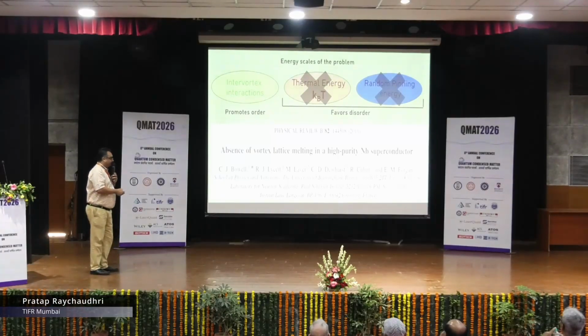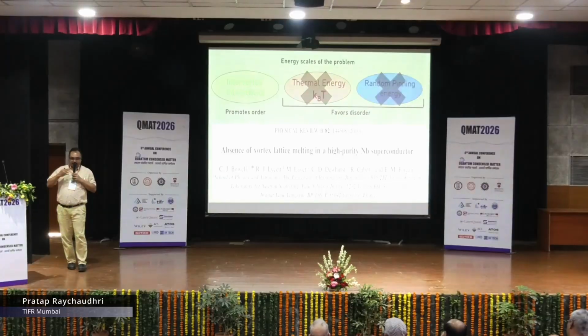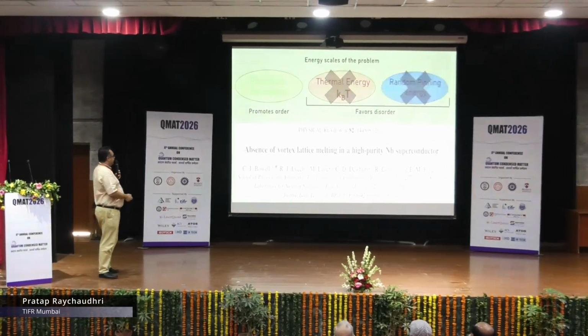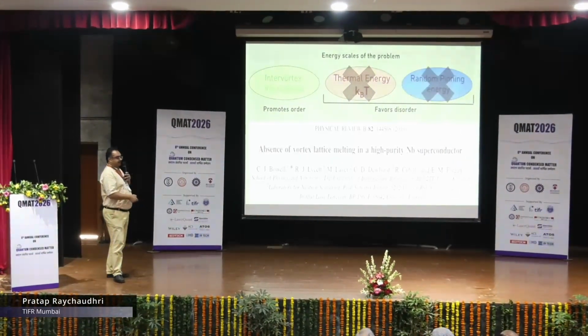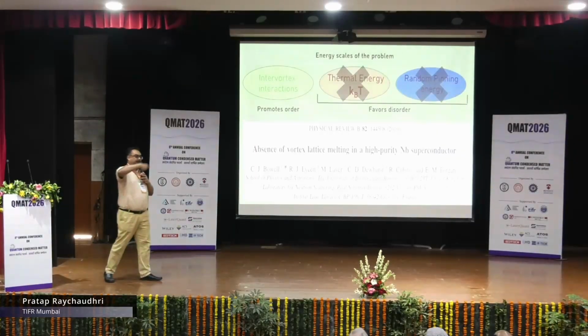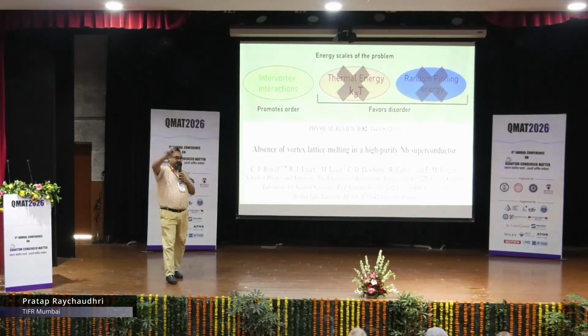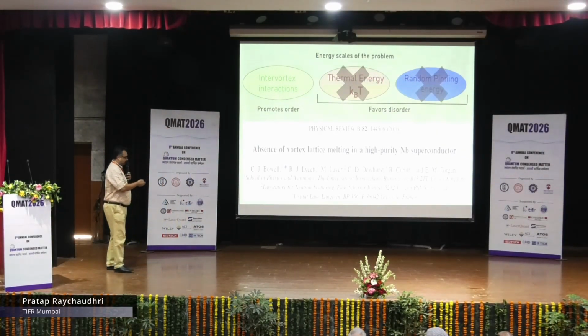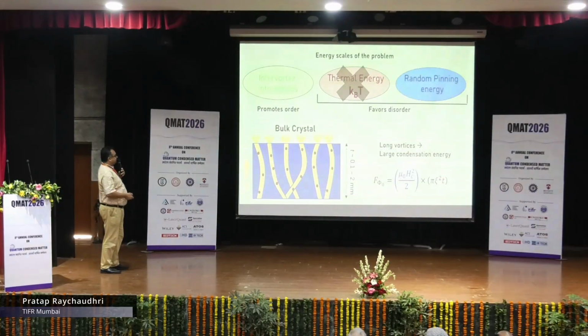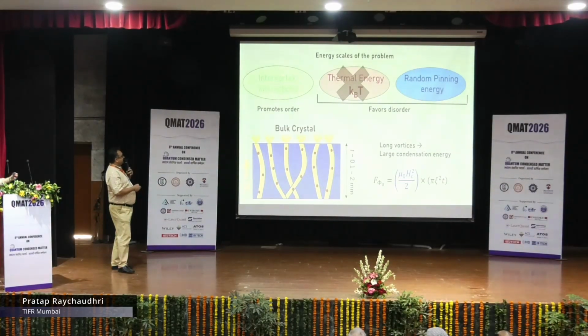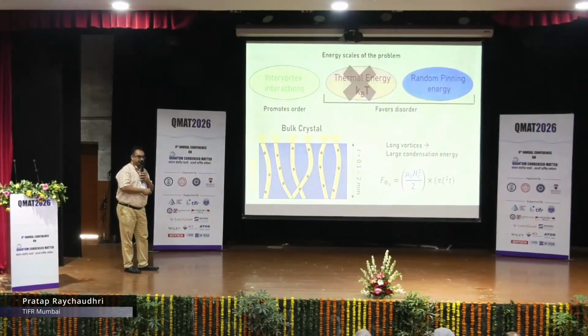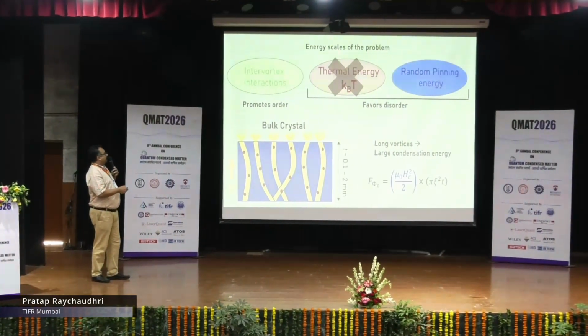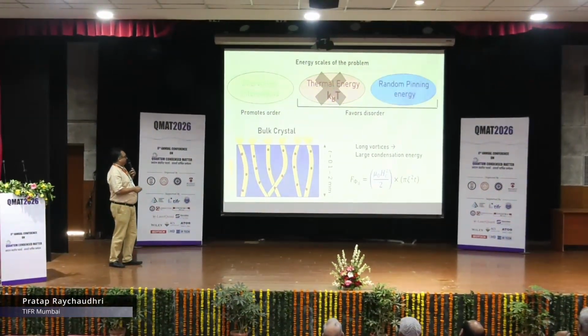Thermal energy is very small, and there are many works. This is possibly one of the first papers which pointed it out very clearly, that there is no vortex lattice melting, not even any disordering. You have a vortex lattice which will remain up to the upper critical field. When you see this order-disorder transition, it's actually not driven by thermal energy. It's a competition between inter-vortex interaction and random pinning energy, and thermal energy plays a very small role.